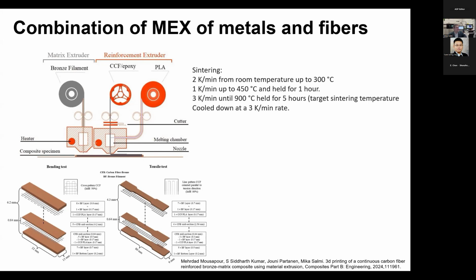But unique here is that we want to really put carbon fibers there, and we know that the carbon fibers will survive in those sintering temperatures. Of course, a lot of those properties are made during the sintering phase. So for sintering, we go 2 degrees per minute from room temperature up to 300. Then we use a slightly slower rate when something starts happening, only 1 degree per minute up to 450, when the binder from the filament starts burning away, and hold it for 1 hour. Then we go slightly faster to 900 degrees and hold there for 5 hours, which was the target sintering temperature, and then cool down.